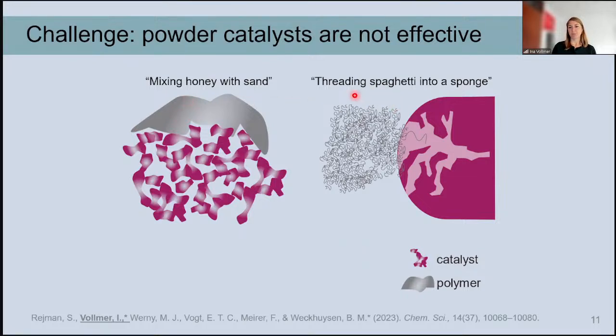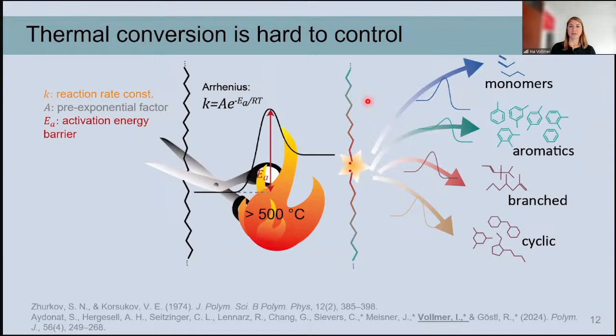And then there's the second problem, and that is that the active sites of the catalyst where the polymer would be converted are inside an intricate network of pores, while the polymer is entangled like spaghetti. So actually getting the polymer into contact with these active sites is as difficult as threading spaghetti into a sponge. And so to solve the problem of the high temperature and the uncontrolled reactions, what if we use force instead of heat?